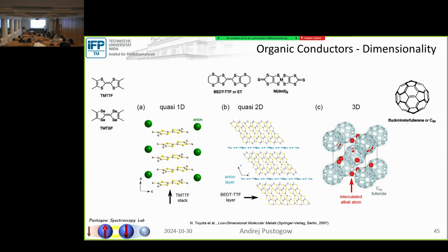So they are very similar to the cuprates in this regard, since they are also quasi two-dimensional layers. And then with these C60 molecules, you have 3 alkali atoms like potassium or sodium, and then you have 1 buckyball, and these form 3-dimensional cubic arrangements. The problem about the fullerenes is only that they do not form single crystals.